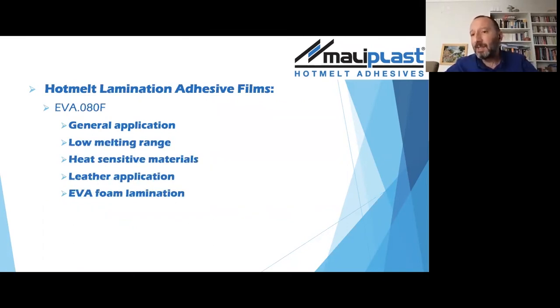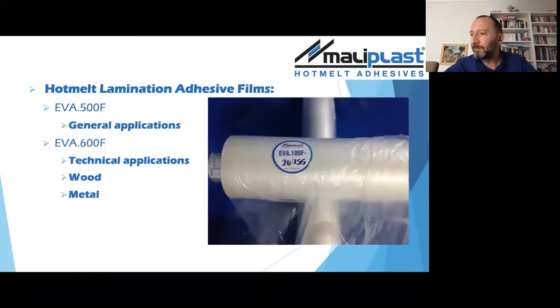EVA 080F is a new product which we developed especially for the heat sensitive material lamination. EVA 080F is a low melt material, even compared to 100F. 100F already has a reasonable melting point around 90-95 degrees. EVA 080F has even lower, at around 60-70 degrees. So it's very good for the EVA foam lamination, where EVA foam is considered a heat sensitive material. You cannot heat up too much. It causes some swelling problems on the fabric surface.